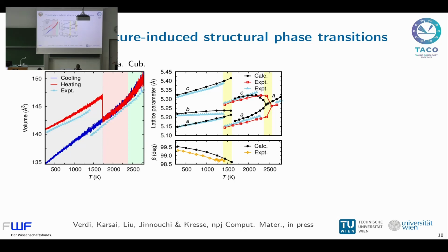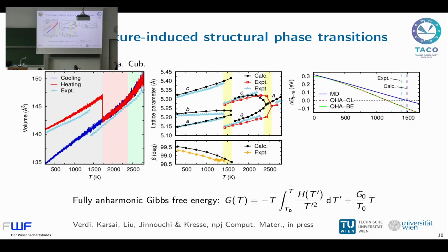And if we look at the actual values of the lattice parameters versus temperature, this is what we get. Again, compared with the experiment, it's pretty good. We're doing DFT with PBEsol, which is pretty accurate, and this is the monoclinic angle. But of course, you cannot extract the transition temperature this way for a first order transition, because you will need to run your simulations forever and in a huge cell. So we needed to do actual free energy calculations.